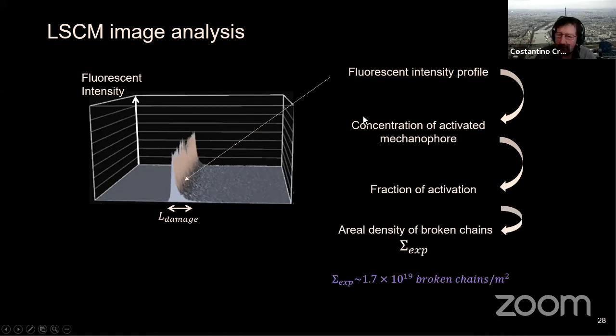From this, you can get an areal density of broken chains in absolute terms, in chains per meter squared, because you actually quantify how many chains you've broken through your calibration procedure. Now, this quantity, which again we get without any adjustable parameter, is pretty consistent with what you would expect from the modulus of your material. From the elastic modulus, you know how many chains per unit area you have.